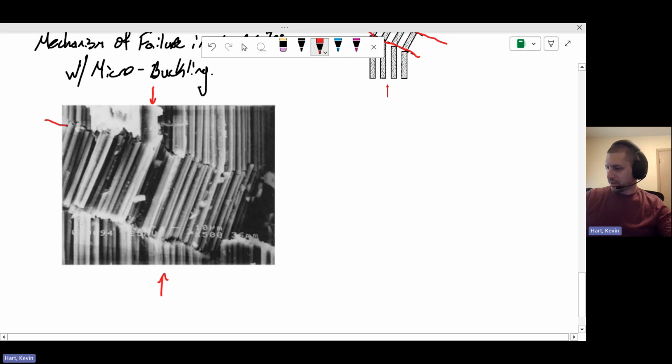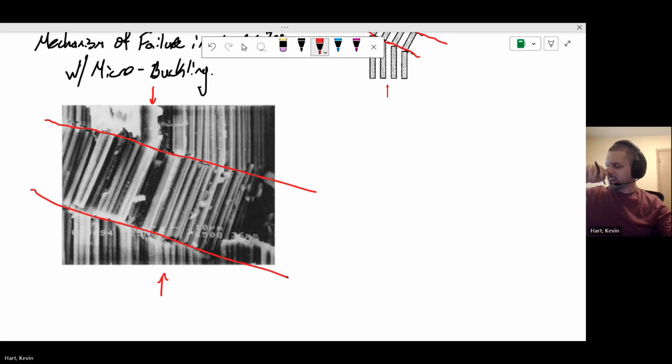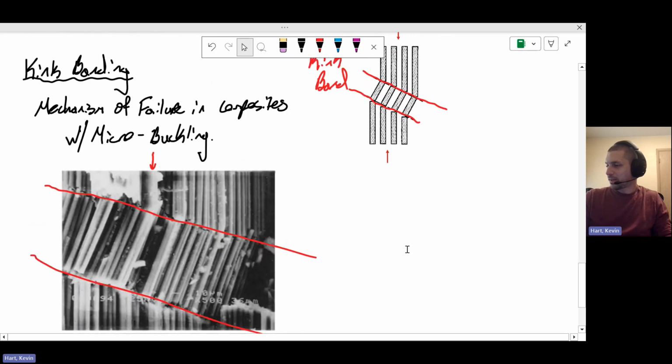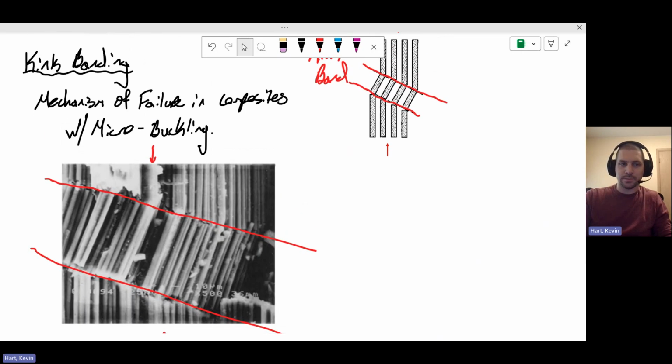And you see that railroad track here now that has occurred. And this is called a kink band, where you've got to relieve some of the compressive strain on the composite. And the way to do that is to cause this thing to kink and give you a little bit of relief, more or less. So that's what's happening there. Kink banding, pretty cool thing. Happens with in-phase microbuckling.